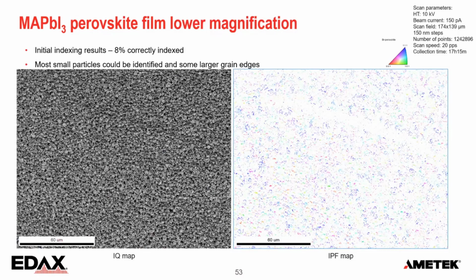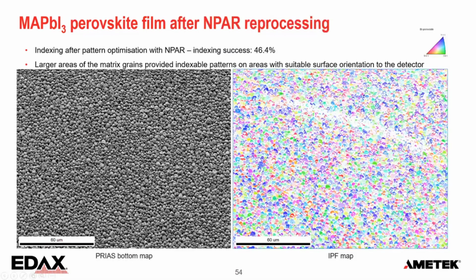Initially, 8% indexed. I was very careful. This took 17 hours to collect. This scan was slow. And here again, initially, we just have the indexing of those small particles. But after NPAR, we can get that. So you have a really nice large area analysis of an overnight run.